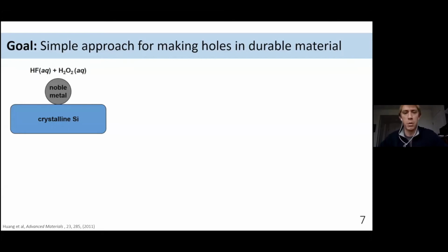So what we did come across was this approach called metal-assisted chemical etching, which was invented about 15 years ago, somewhat by accident. It essentially involves a technique of punching small pores, or actually any size feature, into a silicon substrate. Just for an overview, so we all understand where we're coming from, you essentially would start with a crystalline silicon substrate, as shown on the slide. You would deposit some kind of noble metal feature on that surface, be it silver, gold, platinum, palladium. They all work fairly well in different ways.